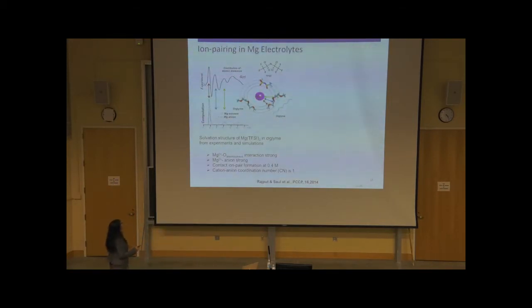To do that, we begin our analysis with a simple salt, magnesium with TFSI anion and diglyme solvent molecule. And we combine simulations with experiments to understand the solvation structure of this magnesium electrolyte, because this is one of the few electrolytes that can show reversible plating and stripping. From both simulation and experiments, we observed magnesium is nicely 6-coordinated by the oxygen atoms of this TFSI anion, as well as the diglyme solvent molecule. And the interaction between magnesium and anion is so strong that it forms contact ion pairs even at 0.4 molar concentration. And I'll explain this sentence.